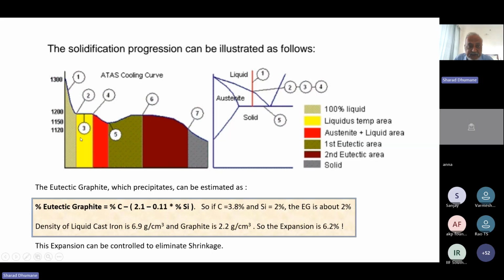So what are the phases here? The first phase is 100% liquid. So at point 1, you see it is 100% liquid. This yellow between point 2 to point 4, what is that yellow? It is the liquidus temperature area. It is coming down up to here. It is liquid. So the phase is purely liquid. And at point 4 now it starts becoming solid.